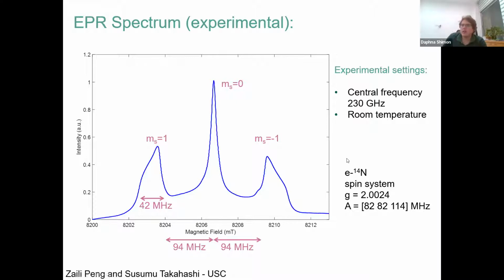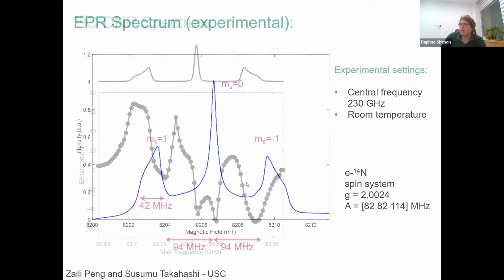And you can see that the EPR line is split into three. It's basically a spin half electron split by the spin one nucleus of the nitrogen, N14. And so there are three manifolds, each one for the different N14 spin state. And we can fit the EPR line with EasySpin and then convert it to 94 gigahertz, which is the field that we did our experiments on.